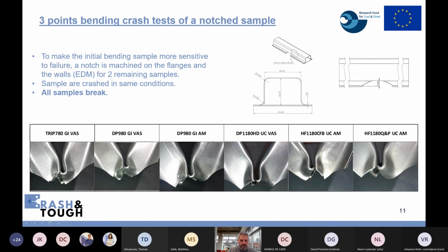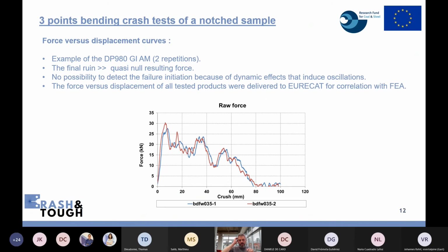We can see that on the next slide, because during this test, we also measure the force versus displacement curves, and we can assume that when the force reaches the level of 0, the sample is completely broken. Unfortunately, it's very difficult to have an analysis of this test in terms of fracture initiation, because of the quite oscillating and noisy aspect of the curve.